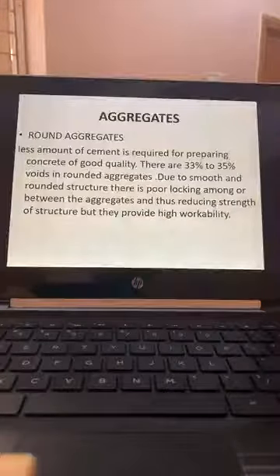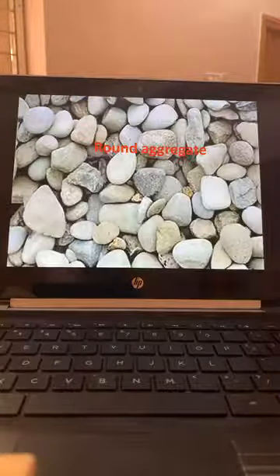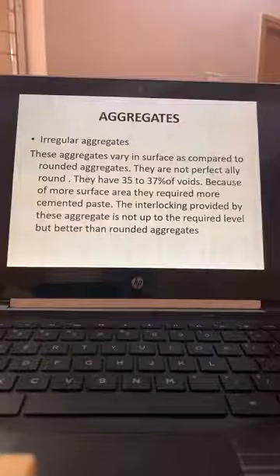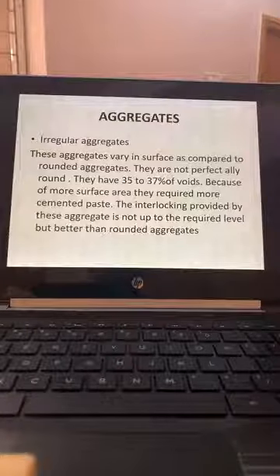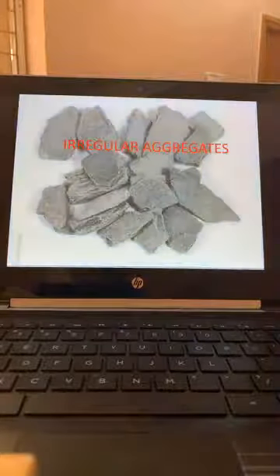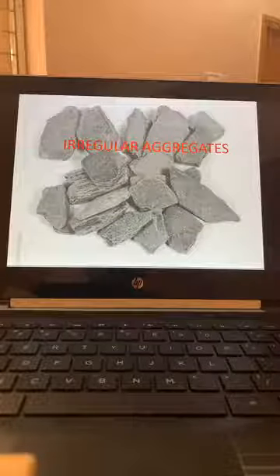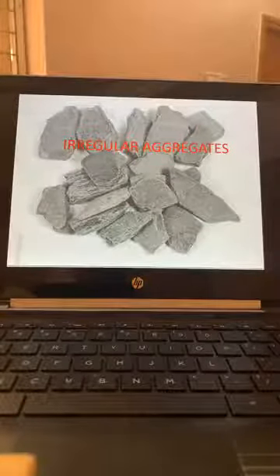For round aggregates there are 33 to 35% voids due to smooth and rounded surfaces — not used for strength concrete but for porous concrete. For irregular aggregates, voids are 35 to 37%, more cement paste is required, but they are good for strength due to interlocking. Flaky aggregates are not good for concrete — by visual inspection we should be able to judge which aggregate is good.